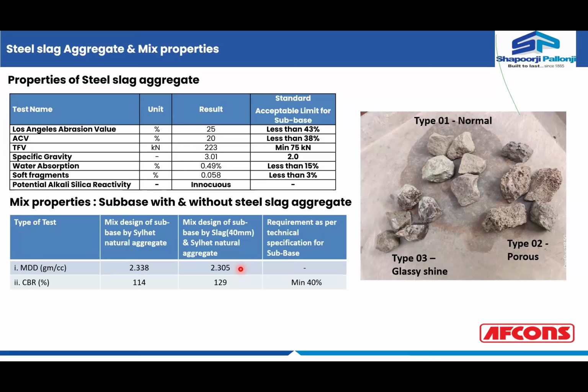Now, when you check the mix properties using the steel slag, in the mix design of subbase with the natural aggregates, the MDD was close to 2.338, whereas if you replace the select natural aggregates with 40 mm steel slags, there is a slight drop in the MDD values, but it has not deteriorated the properties of the mix, because the CBR has moved from 114 in the case of naturally available materials to 129 in case of steel slag.